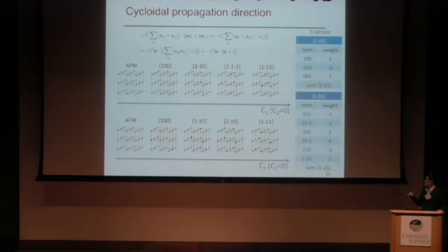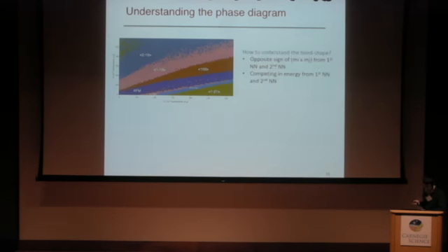And if both C1 and C2 are finite, the contribution will simply be a summation of the C1 terms and C2 terms. To understand why each magnetic configuration forms this kind of bands extending with increasing C1 and C2, the reason is that the C1 terms and C2 terms are competing. If one energy is positive, the other one will be negative. The reason is this Mi cross Mj term, because one is the first nearest neighbor and the other one is second nearest neighbors. And the BFO is the G-type AFM, so that gives opposite sign of this cross product.